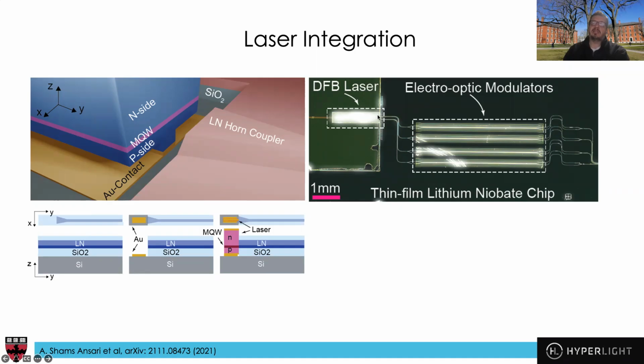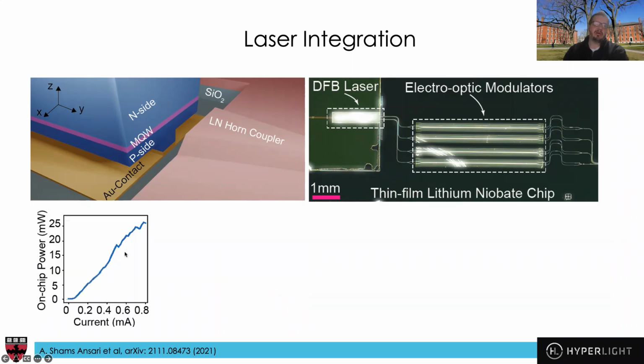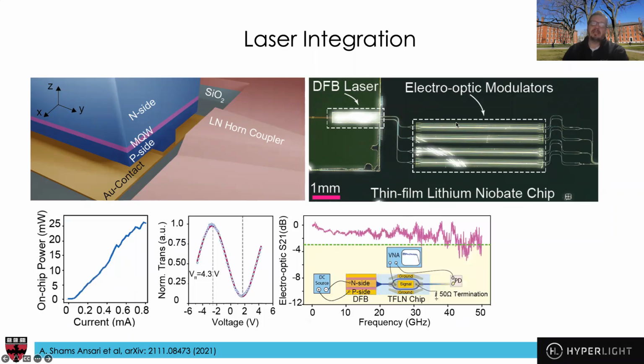We are able to get about 60 milliwatts of light. The laser has about 200 milliwatts, actually 180 milliwatts or so. We're able to get about 60 milliwatts in the waveguide, and after we are done with everything, with the modulator, we get about 25 milliwatts of power. The nice thing is that this is integrated with a high-speed modulator. So we have the DFB source and amplitude modulator here that can be run at, we demonstrated, 50 gigahertz. Theory says that this should operate up to 100 gigahertz, but this bandwidth was limited by a photodiode that has a roll-off at about 40 gig.